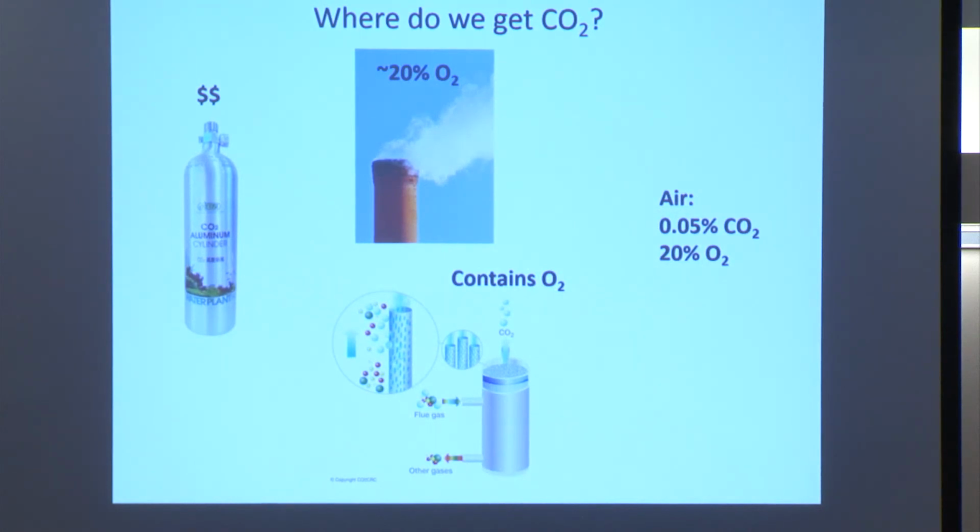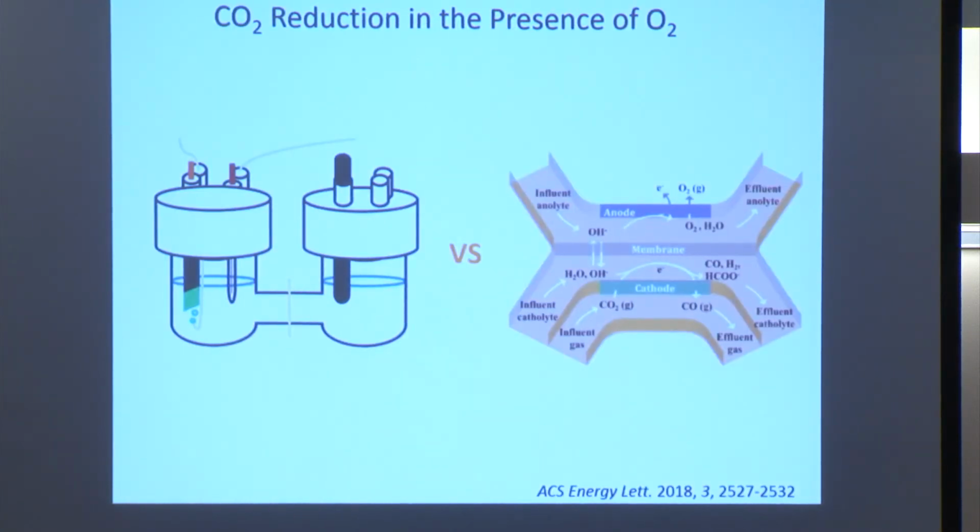If we think about reduction of CO2 versus reduction of O2, O2 is certainly the easier one, right? The redox potential thermodynamics is 1 volt easier compared to CO2. Then what would happen if we reduce CO2 in the presence of O2? It depends on what reactor you use. If you use a reactor where the oxygen is dissolved in the liquid, then because the oxygen solubility is so low, it can be diffusion controlled, so it's not so big a problem, but you are not looking at the real kinetics, right?